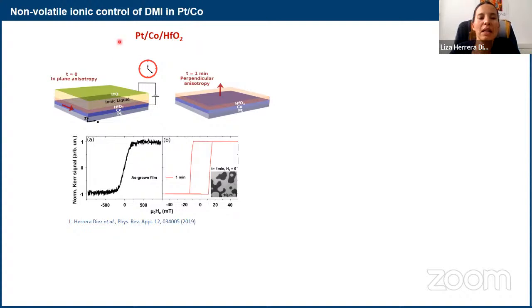So here is platinum cobalt hafnium oxide. I told you before, we're using hafnium oxide because it's known to have a high oxygen mobility. So here what we did is to put the ionic liquid on top, we apply the voltage, in this case a negative voltage, and then we remove completely the ionic liquid. So it's a non-volatile effect. So then we can really afford to just take the gate out of the device completely and then use it for measurement or for patterning or for anything else.